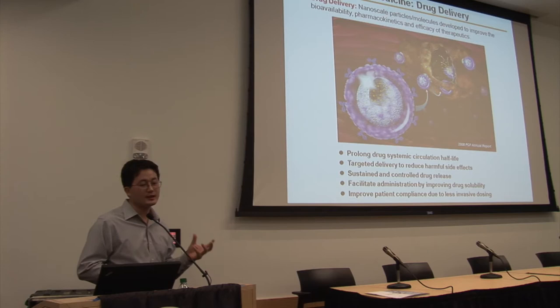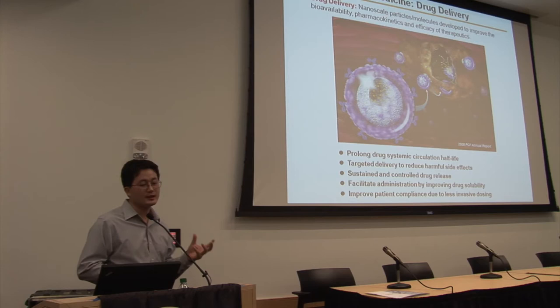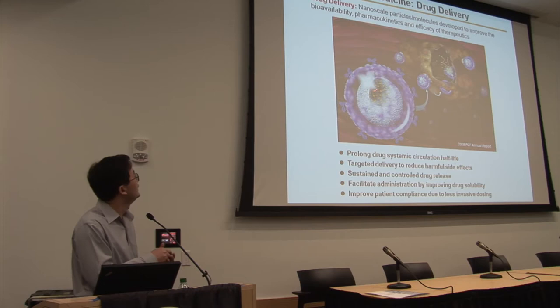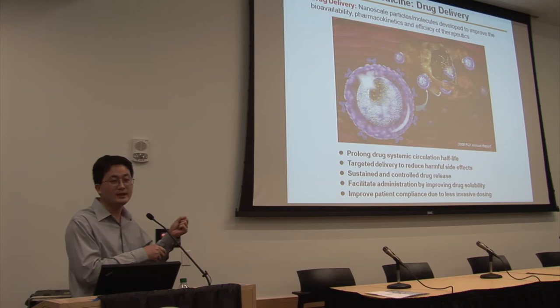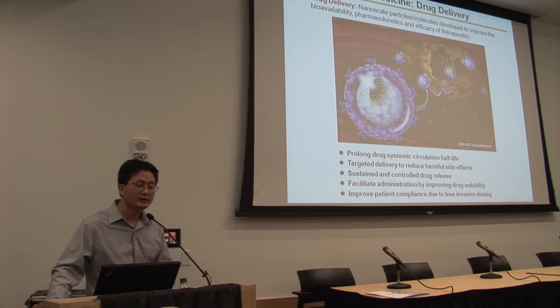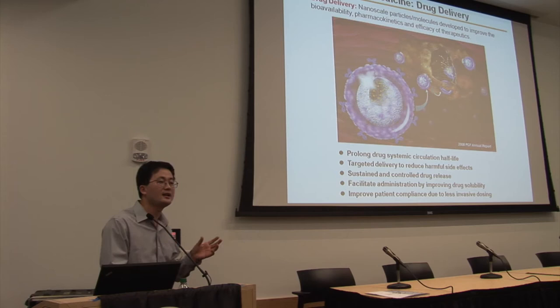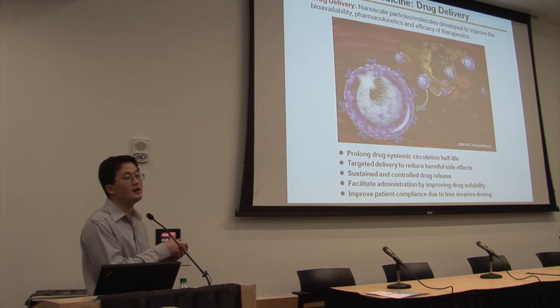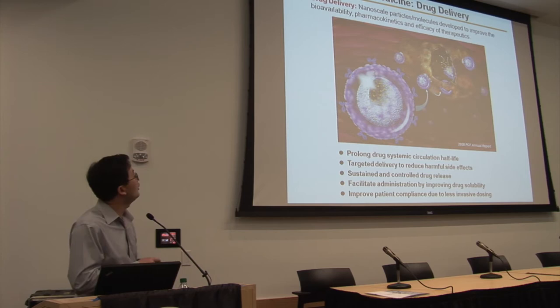This cartoon gives a very good summary of what nanoparticle drug delivery is. You have a blood vessel with a diseased cancer cell. A typical nanoparticle has a core-shell structure — a hydrophobic core where you can load hundreds and thousands of drug molecules, protected by a hydrophilic shell to prolong circulation lifetime. On top of the shell are targeting ligands that can recognize cancer-specific antigens overexpressed by cancer cells. When these particles circulate in the bloodstream and find the cancer cell, they bind and trigger endocytosis. Once internalized, they release all the cargo in a controlled, sustained, or burst manner to kill the cell.